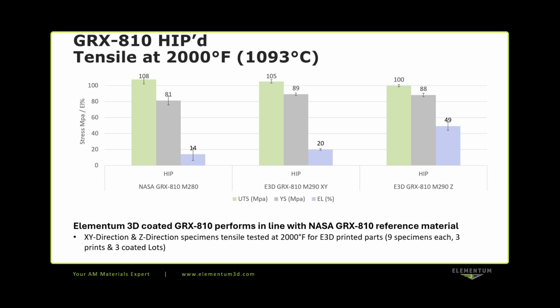So now looking at GRX 810 produced in an EOS M290 in the case of the Elementum 3D comparison data, and the NASA reference data produced in EOS M280 system. And looking at the HIP condition, tensile properties at 2000 degrees Fahrenheit or 1093 C. And the Elementum 3D coated GRX 810 again performed in line with the NASA GRX 810 reference material.